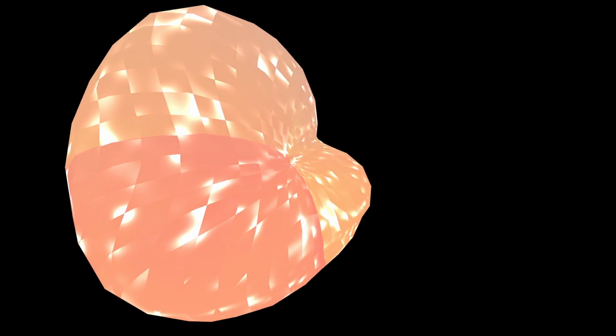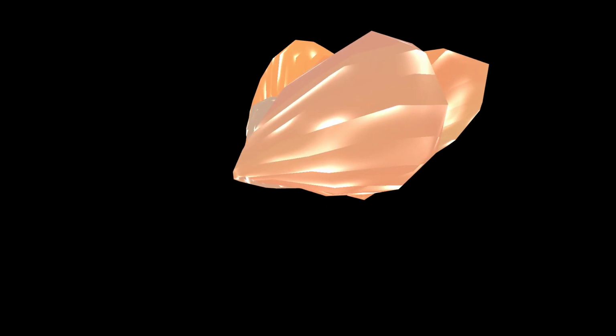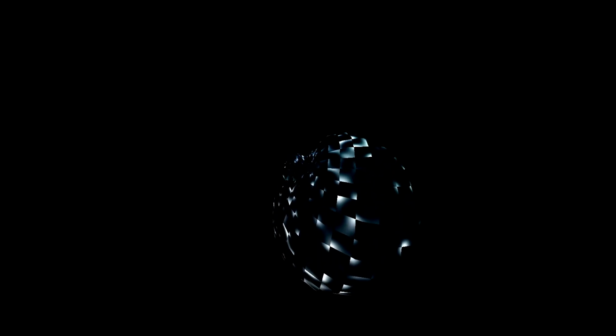binding energy. And that binding energy is like a fingerprint. A fingerprint for the element. Yes. It's unique to each element. But even better, it's slightly shifted depending on the chemical environment around the atom. Like whether it's an oxide or a pure metal. Exactly. It reveals the oxidation state, what it's bonded to. Yeah. So XPS tells you what's there and how it's there chemically. Hugely important in materials science, developing catalysts, understanding corrosion, loads of fields. I can see that. Knowing the exact surface chemistry must be critical.